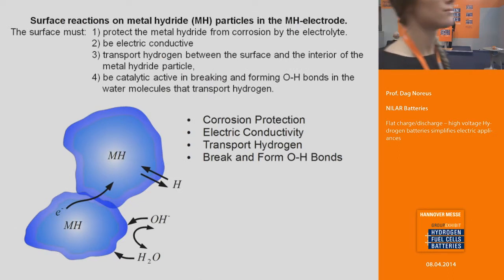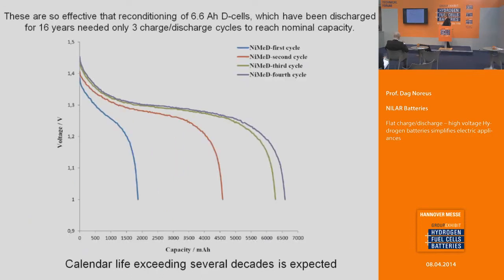And this is all done because we have better control now of the surface. The surface is the trick of the metal hydride. This is in small letters, but the surface reaction should protect the hydride from corrosion, be electrically conductive, and it should transport hydrogen between the surface and the interior of the metal hydride particle. And it should also be catalytic in breaking and forming this OH bond. The chemistry is mostly in the OH bond here. Similar to the lithium battery, where it is the oxygen-lithium bond that is transmitted. You have all these transition metal atoms just to have a suitable oxygen in a way for this. And this is a fairly well-controlled process.